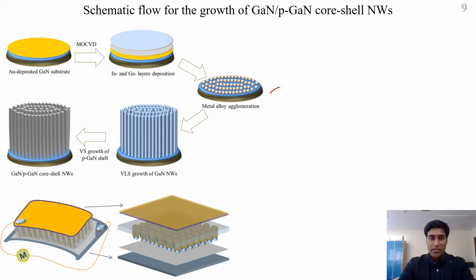So after the agglomeration step, the growth of the nanowires was started, by introducing the growth species like ammonia and trimethyl gallium for around 500 seconds at 50 torr. So after the growth of pristine nanowires, in the same experiment, we started the growth of the p-GaN shell. Here you can see, this is the p-GaN shell.